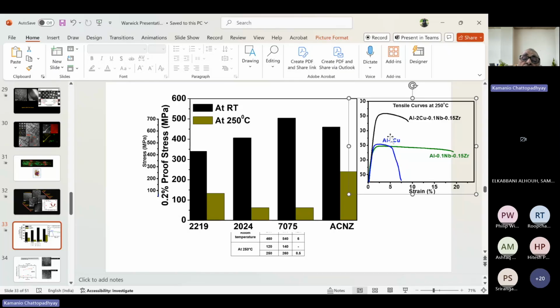At room temperature, they are not very different. Still, ACNZ, that is our alloy, is still very high compared to the 2024. But the high temperature strength of our alloy actually surpasses the 7075 alloys. So we are very close to what challenge Boeing had given us, that 250 megapascal at 250 degrees centigrade.